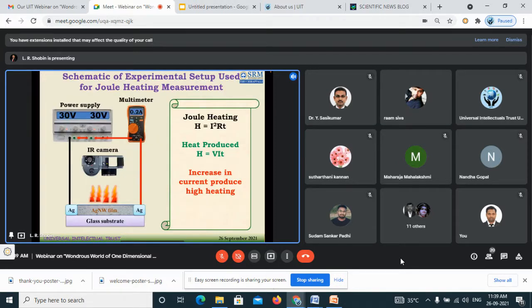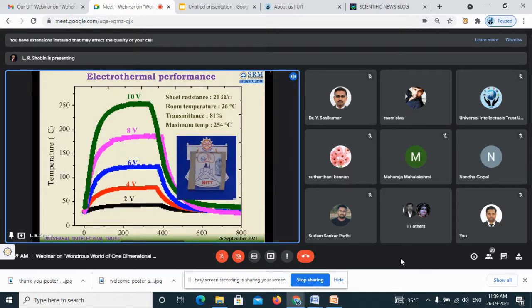So again, the process is very simple. I want to measure the heating effect of this film. So I just connect it with the power supply. I have connected a multimeter in series in order to measure the resistance of the films or the current flowing in the films, and I measure the heating temperature with the help of an IR camera. So if I power on, say for example, supplying 10 volt, the temperature of the film will increase and reach a steady state. And if I switch it off, cancel the power supply, then it will gradually return to room temperature.